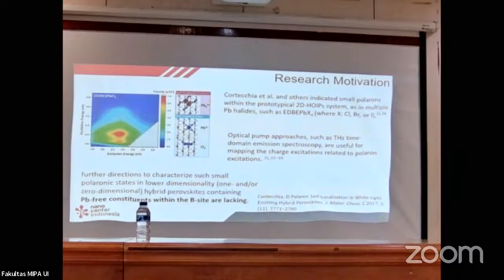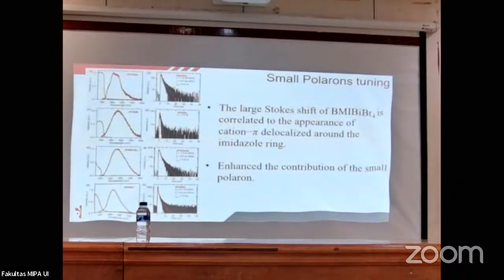So we just took for granted that as soon as we see from the PL signature that, for example, the line shape of the PL at the longer wavelength is slightly tailed to the end of the line, so it doesn't look like a symmetrical shape, that's one thing we can say, aha, we seem to have a polaron here. Again, this is from the previous finding by Cortecchia. When you see this kind of line shape in the photoluminescence data, where the data start with a very nice landscape, and then all the way at the longer wavelength you see a very weird shape. Usually the PL will be symmetric when you have a nice central symmetric case.